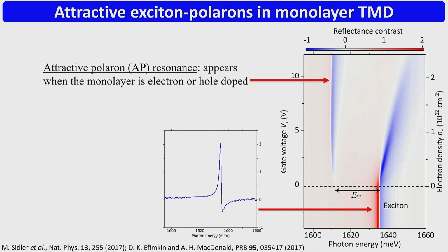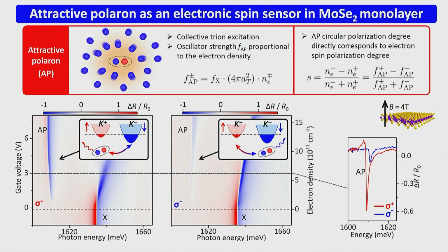Right? So in this case, we will be mainly interested in this lower energy new branch, which we have called an attractive polaron resonance. So I'll use the acronym AP. It's only there when we dope the system. What's more is that it's only sensitive to a given polarization of the incident light. So if the electrons are occupying this spin down state, this spin valley state, then I can see this resonance strongly in sigma plus polarization, and I see very little in the sigma minus polarization, because in this case with the magnetic field, I made sure that most of the electrons occupy this valley.